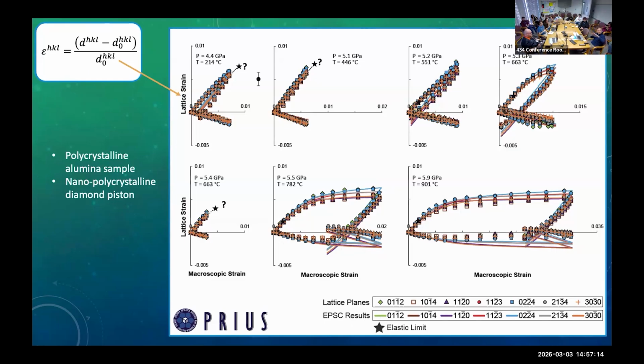So you don't consider nearest neighbor interactions, whereas in the real world you have near neighbor interactions that can drastically change the stress state. Although anything you're going to see in diffraction is an average of a lot of things, right? The diffraction does not come back to a single place. It's a mess all over the place, which means that different groups of grains are doing different things, and there are enough of them to give you a diffraction peak that gives you a different lattice strain.